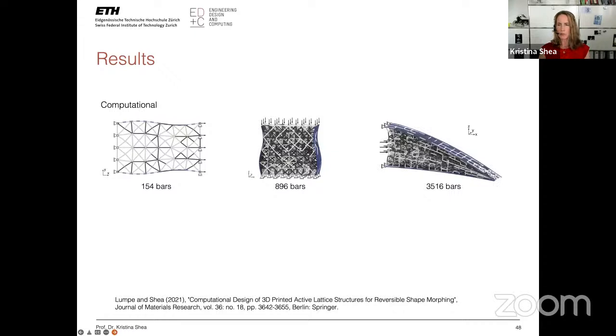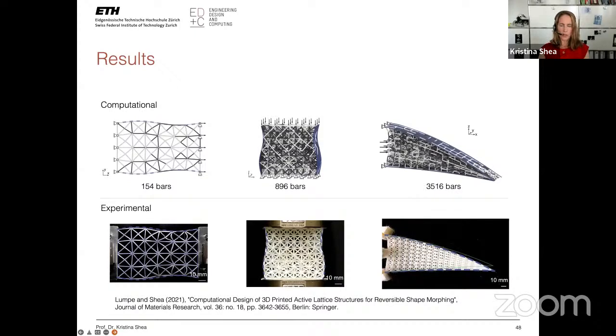And those are the 2 different materials distributed in the structure to create the deformation that was defined as the goal. And so he also 3D printed these and then experimentally tested them. The 2 on the left-hand side, so the 2D and the 3D lattice, are tested in an Instron machine using a temperature heat chamber in the Instron machine. And the one on the right-hand side, the airfoil, that's tested using a water bath for this uniform temperature.